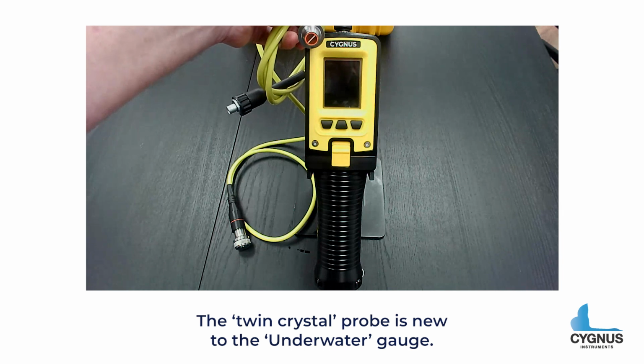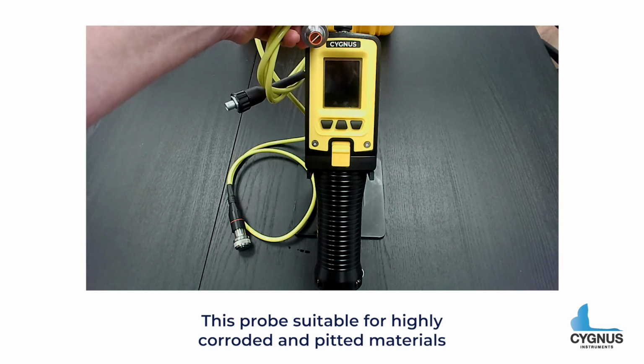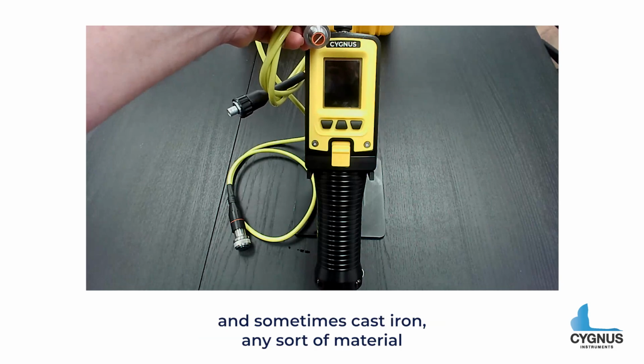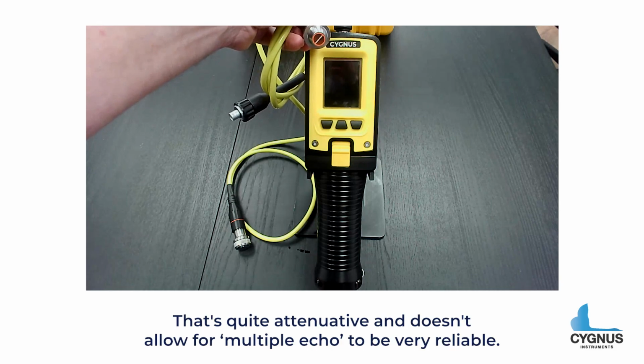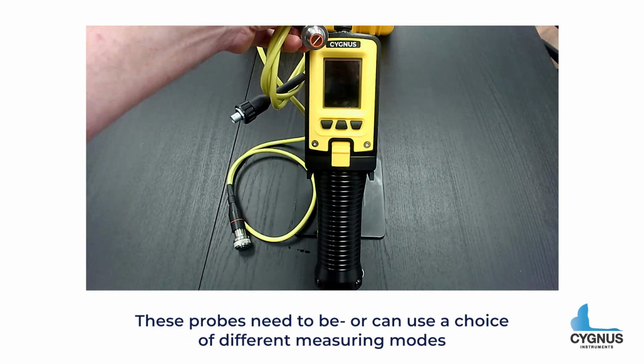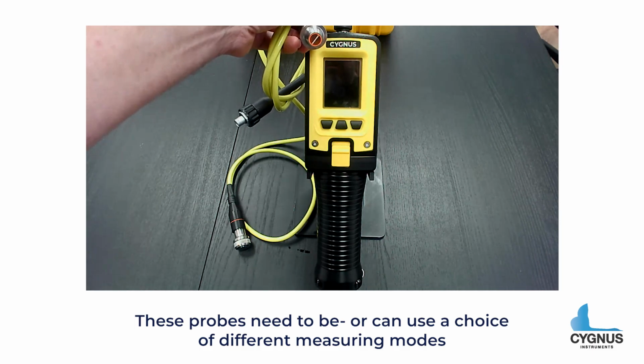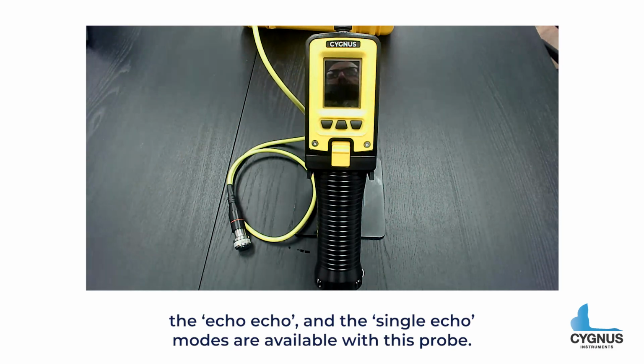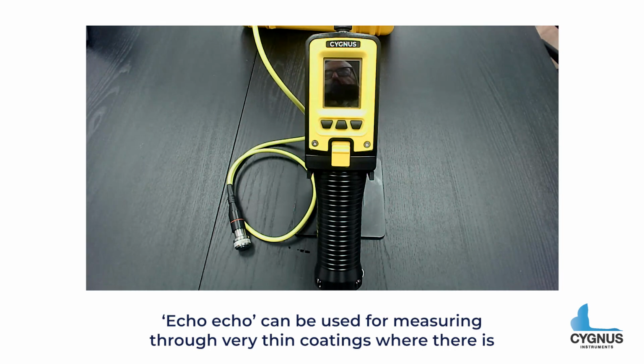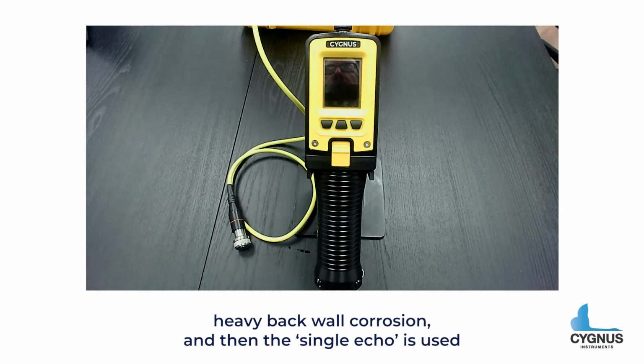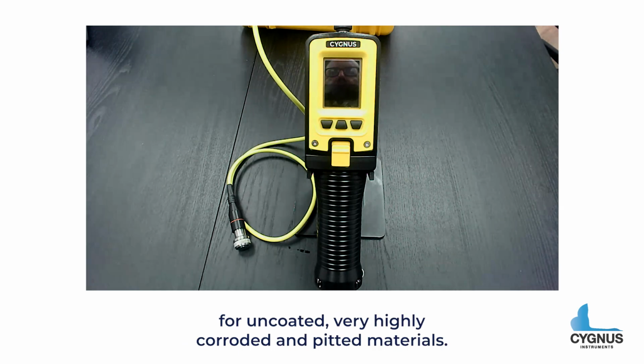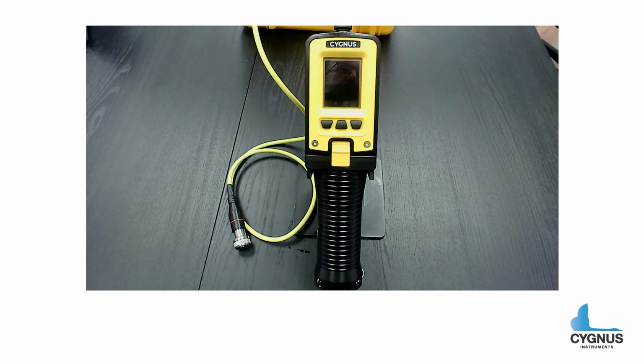The twin crystal probe is new to the underwater gauge. This probe is suitable for highly corroded and pitted materials and sometimes cast iron, any sort of material that's quite attenuative and doesn't allow for multiple echo to be very reliable. These probes can use a choice of different measuring modes. The echo echo and the single echo modes are available with this probe. Echo echo can be used for measuring through very thin coatings where there is heavy backwall corrosion. And then the single echo is used for uncoated, very highly corroded and pitted materials.